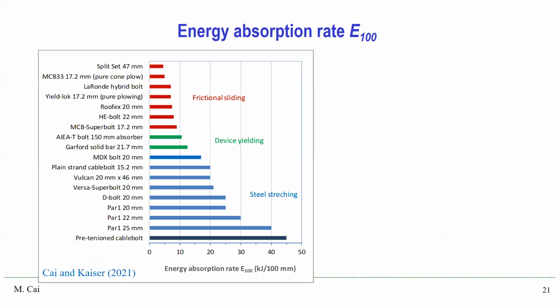Another important factor to consider is the energy absorption rate. This energy absorption rate is defined as the amount of energy absorbed per 100 millimeter bolt displacement. We use E100 to represent this energy absorption rate. And you can see from this figure, rock bolts with steel stretching as the energy consumption mechanism have higher energy absorption rate than other bolts.